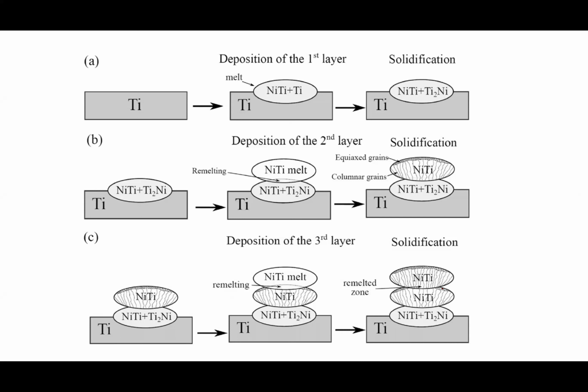On the top area of the second and the next layer, equiaxed grains were formed. However, these zones are completely or partially remelted during the deposition of the consequent layer, and these remelted zones solidify together with the consequent layer, leading to the formation of columnar grains. The top region of the fifth layer has retained equiaxed grains, as this region was not remelted unlike the other layers. In a similar fashion, we could see the structures of the fourth and fifth layers were so close to each other. Consequently, these layers underwent the B2 to B19 martensitic transformation in the same temperature range. Moreover, the chemical composition of the dendrite matrix in these layers was close to the composition of the wire used in the deposition.